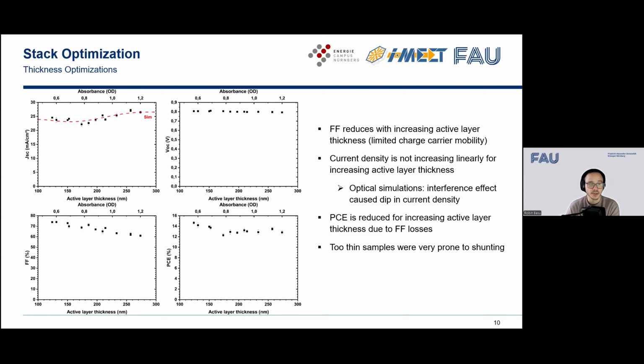And not only the ETLs play a big role, of course, again, the active layer thickness has some effect on the efficiency of our devices. Because what we usually see as a trend, the thicker we make a layer, if you just think about it, you should absorb more light. However, due to the restricted charge carrier mobility, you would also lose in fill factor in your devices. So to show the trend, we actually fabricated devices with different active layer thicknesses and had a look at the trends that we can see.